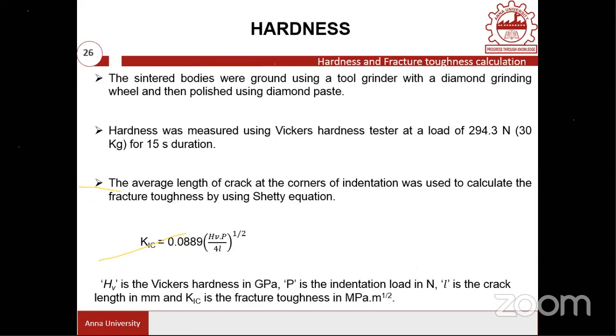But here, the crack propagation depends on the stress intensity in the ceramics as well as in the CERMETS. Therefore, one cannot simply take the area under the stress strain curve as equivalent to the fracture toughness value. It is something like a non-approved procedure. Therefore, there is a procedure proposed by Shetty, where you can measure the fracture toughness from the cracks emanating from the indentation surface. That is the methodology that we have employed here.